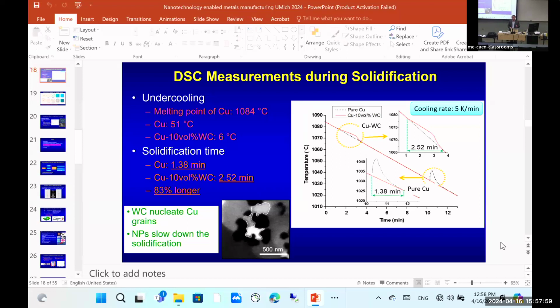Traditionally, it's all chemistry based. You rely on chemistry, solute enrichment, to block the growth. But atoms are free and they move so fast, diffusivity is so high in the liquid state. But nanoparticles don't move very fast. They're almost like bikers on the highway compared to the cars. Originally we treated that as a weakness, but right now in this case it is an advantage, right? You slow down like that.